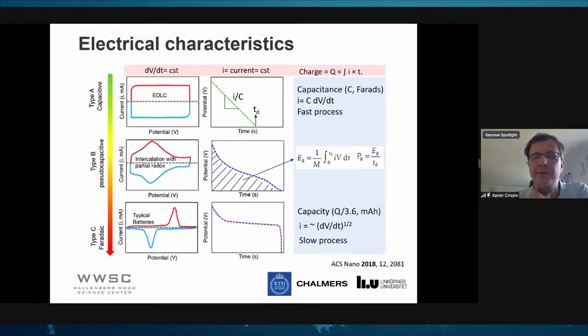As I told you, there is no specific threshold like electrochemical behavior. On the contrary, if you go to the bottom here, there you have a specific feature of an electrochemical reaction going on in the solid. So you see specific peaks appearing in the cyclic voltammogram. You have these peaks, so you have an electron transfer reaction inside the solid. And at those potentials, you will have a very specific threshold, basically. So you have a constant potential versus time until all the redox reaction has happened. Then, when the redox reaction has occurred in the solid, there is nothing more to be done. Then the potential suddenly drops, basically.